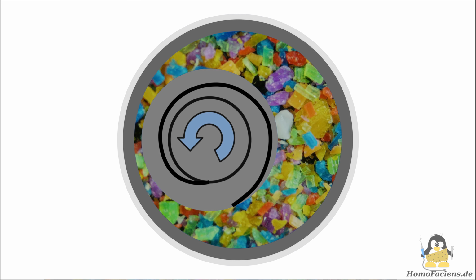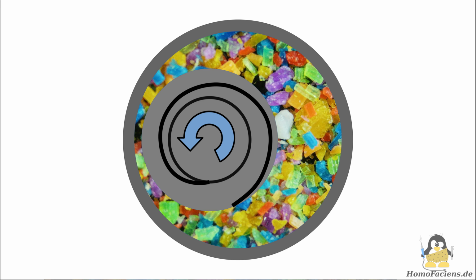The wood screw acting as the auger is not positioned centrally, but rather so that it almost touches the wall at one point. On the opposite side, the gap to the extruder wall is correspondingly larger. This gap is necessary to allow the air trapped in the powder to escape and for pressure equalization to occur. The simple wood screw has a constant pitch and core diameter.